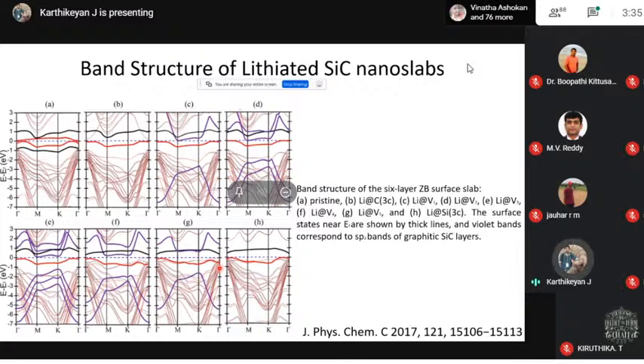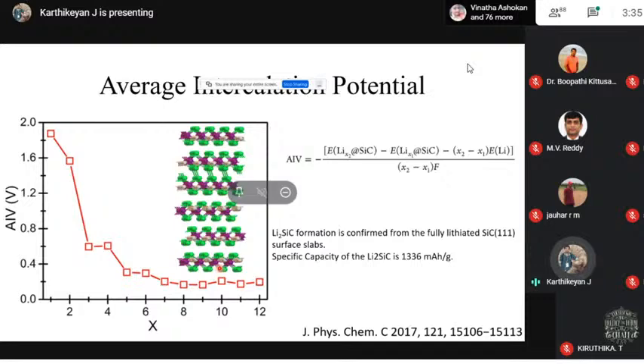The mechanism of this anode material was really not understood previously, but so many people started using silicon carbide as a nanomaterial. So we added more and more lithium, and we wanted to see how much lithium this can store. Actually, in the earlier work on tin based materials, we didn't go for the capacity calculation, because we took a very long CNT model. If you add lithium on every hexagonal ring, that's going to be a very computationally heavy job. So we didn't do that. But here it was a very easy job.